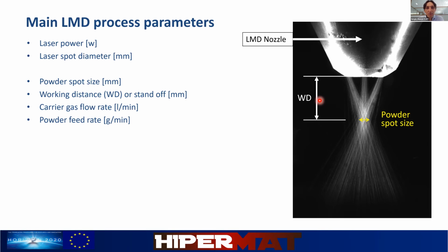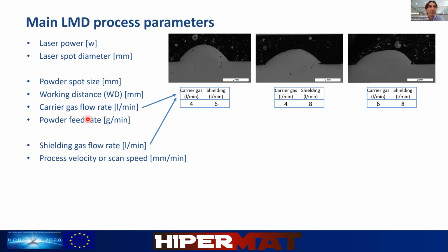The carrier gas flow rate is the liters per minute of the gas that carries the powder, which is usually argon. And the powder feed rate is the grams per minute of the powder that pass through the nozzle. We also have a shielding gas flow rate, which we have seen before, to protect the melt pool from oxidation.